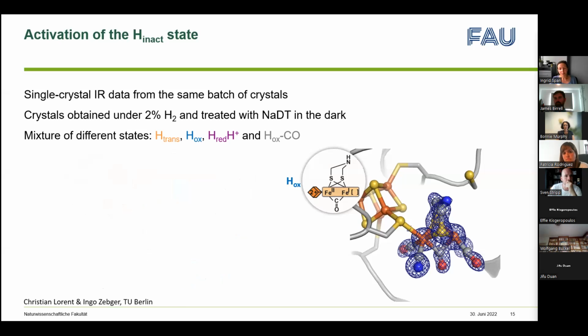So as I already mentioned, we are also trying to characterize our crystals using single crystal spectroscopy, and we collected IR data for several crystals that we set up under these conditions. This was also done by Christian and Ingo in Berlin, and we tried to freeze crystals from the same batch for IR spectroscopy, and we not only tried, we were able to freeze crystals from the same batch.